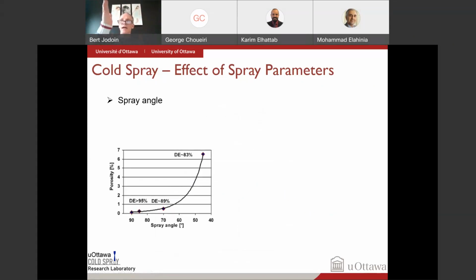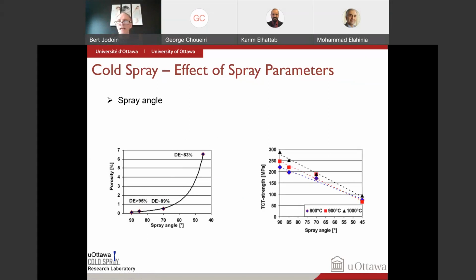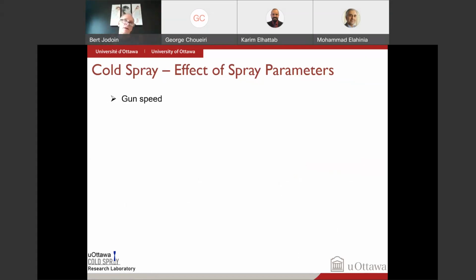Spray angle, so you can spray at 90 degrees or change the angle. Well, if you change the angle, of course, the normal velocity compared to the substrate drops, and you're going to get a decrease in deposition efficiency and an increase in the porosity because they won't deform as well. Same thing in the tensile properties of the coating or the parts you're producing using that. As you increase the spray angle, the properties will go down.